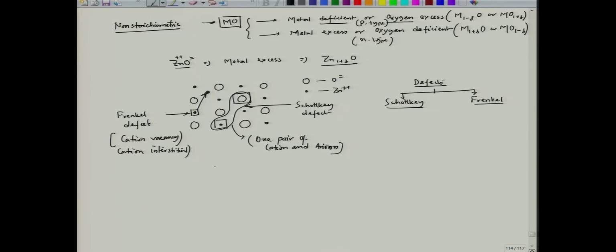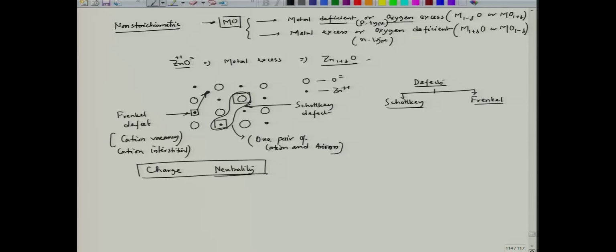And another important aspect in this oxide is that we have to maintain neutrality. When we talk about neutrality, I am talking about charge neutrality. So, this is to be maintained in the oxide, and accordingly we will have different situations, depending on whether it is metal deficient, metal excess, oxygen excess or oxygen deficient. We can generate different types of defects as well as missing sites, and we can have differences in their charge carrying mode. In one case positive holes carry the charge, and in another case electrons will carry the charge. So, at least for zinc oxide, I will see that particular situation again.